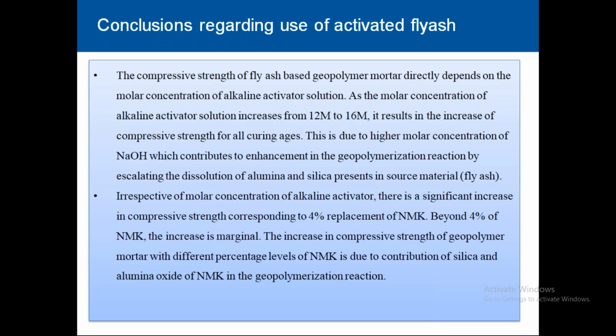So what we can say is that compressive strength of fly ash based geopolymer mortar directly depends upon the molar concentration of alkaline activator solution. As the molar concentration of alkaline activator solution increases from 12 M to 16 M, it results in an increase of compressive strength for all curing ages. This is due to higher molar concentration of NaOH, which enhances the geopolymerization reaction by escalating the dissolution of alumina and silica present in fly ash.